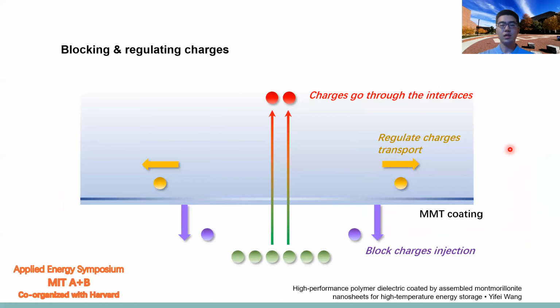So this figure shows the mechanism, a schematic illustration of these coatings. Some charges are injected from the electrodes, and some of them will be blocked at the surface because the MMT coating has a large band gap. There are also some charges that are regulated, dissipating along the in-plane direction because this MMT has a relatively higher surface conductivity. Only a few charges can finally go through these interfaces, and this part of the charges contributes to the final conduction loss.